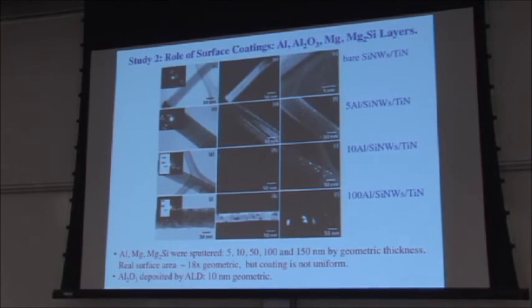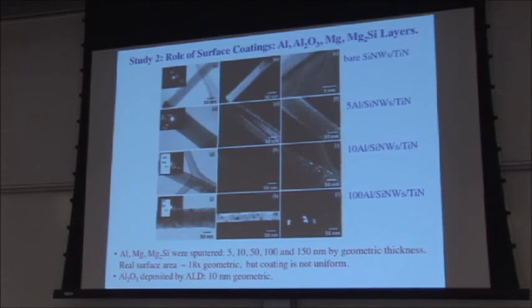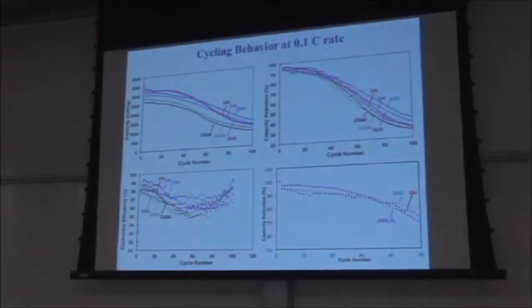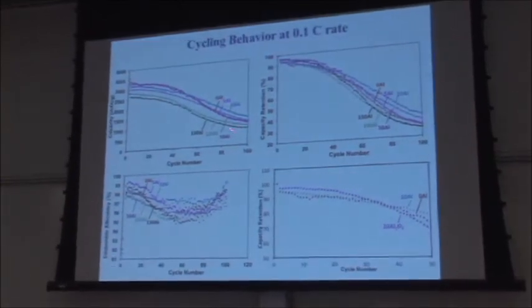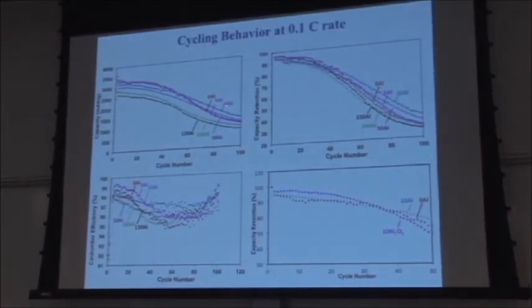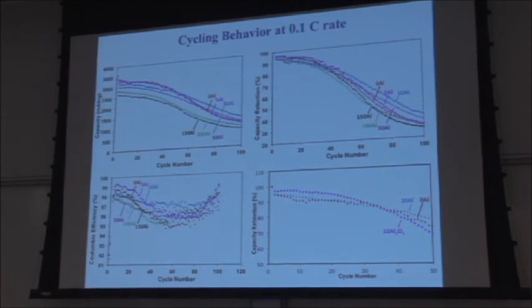but not entirely. We also played around with aluminum oxide deposited by ALD, which is a completely conformal process given our geometry, and we had 10 nanometers by geometric, so about a nanometer roughly, or maybe less, of aluminum oxide. So if you look at the cycling behavior, our baseline is the red, so 0 aluminum, and we do get, it's not a major improvement, we were hoping for a major improvement, and we didn't get it, at least not with these coatings. We have some other ones that are submitted that did give a major improvement.